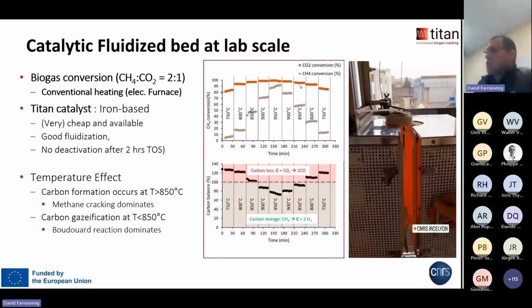And if you measure the carbon balance, you can see that at temperatures higher than 850 degrees C, methane cracking occurs and you produce carbon. You will see that in the next slides. Whereas if the temperature of the reactor is below 850, then the carbon is gasified by the Boudouard reaction and you produce carbon monoxide. So it's anyway crucial to operate at high temperature, from a thermodynamic point of view, and to produce the carbon.